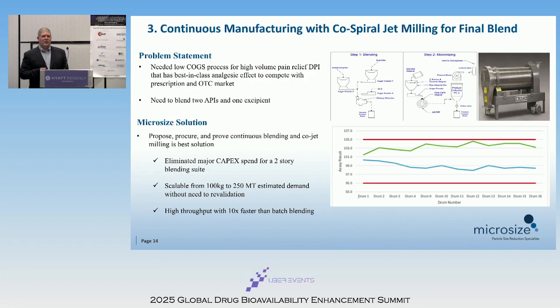We've done this on commercial scales where we employ continuous manufacturing, where we pre-blended the material in a ribbon blender and fed directly into a spiral jet mill. We did this on a compound that was being formulated for a DPI, where we had 2 active ingredients and 1 excipient. And we were able to basically scale this from 100 kilograms up to 250 metric tons. So we're able to move a large volume of material without having to put a major CapEx expense to run this in batch mode. And we got excellent data.